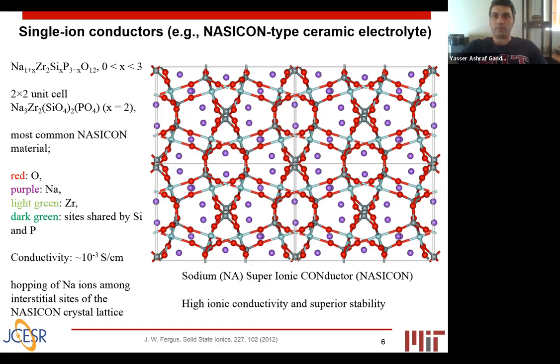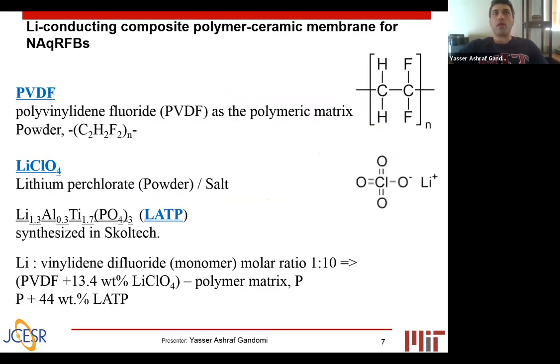Exceptional and ultra high durability, along with high conductivity in the order of millisiemens per centimeter, are the major properties of NASICON-type electrolytes. For the application of non-aqueous redox flow batteries, we are interested in composite polymer ceramics to tune the mechanical and electrochemical performance. We have used PVDF as the polymeric matrix. PVDF has been widely used for lithium solid-state batteries. We are also using lithium perchlorate as the salt for increasing the ionic conductivity, and NASICON-type LATP structure, including lithium, aluminum, titanium, phosphorus, and oxygen.